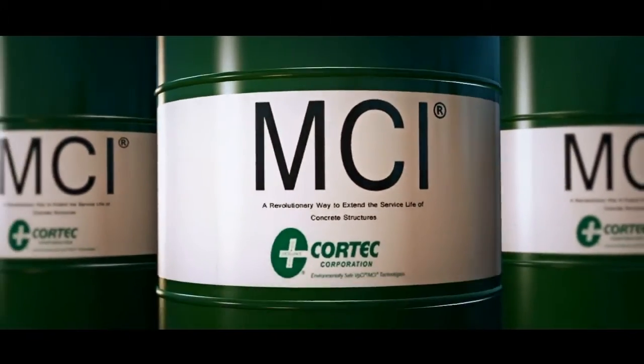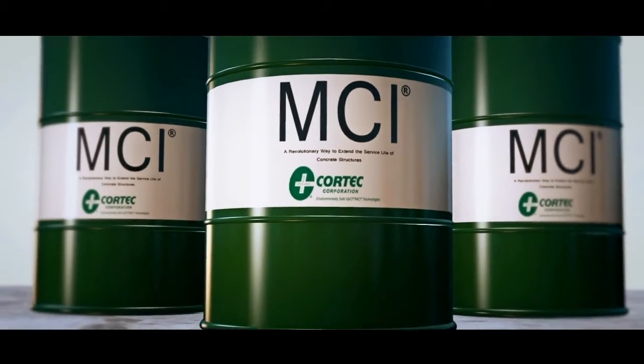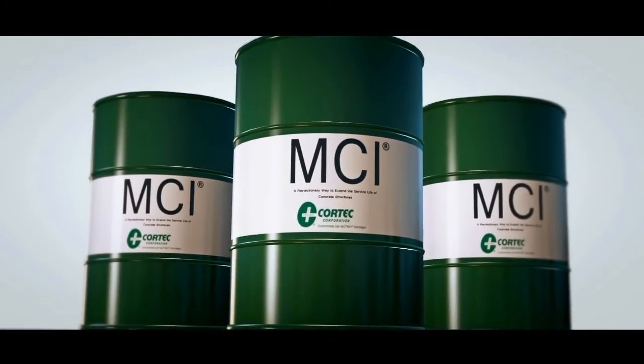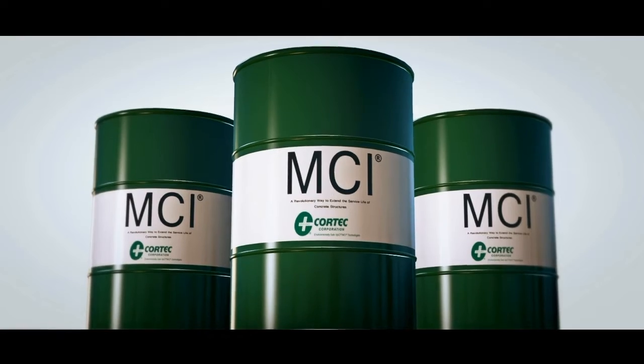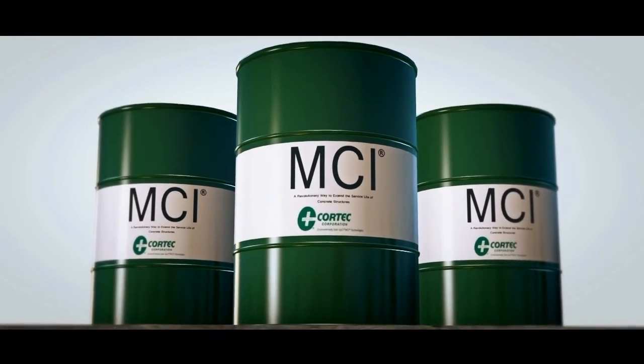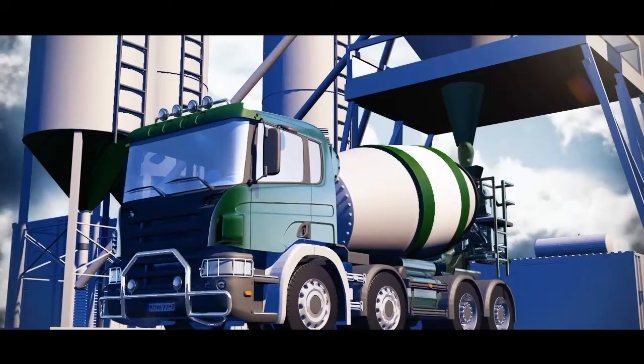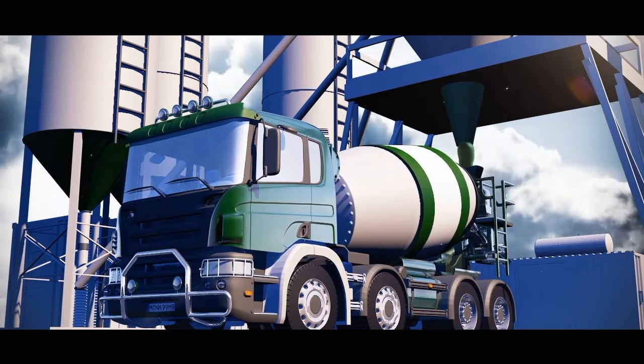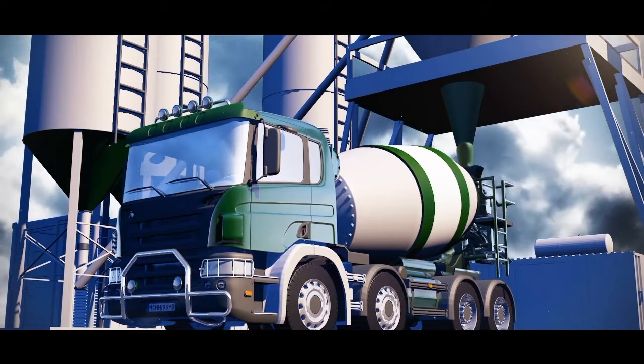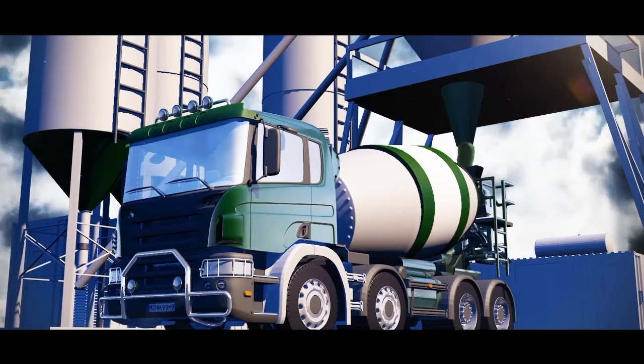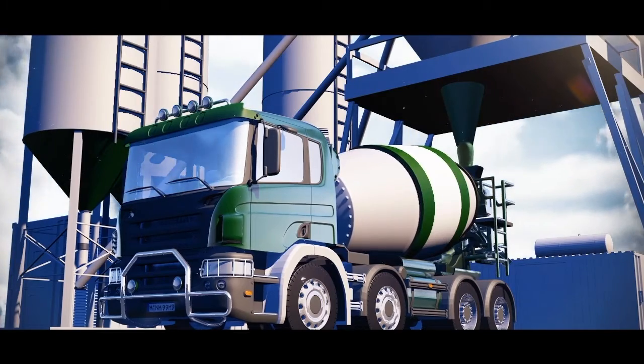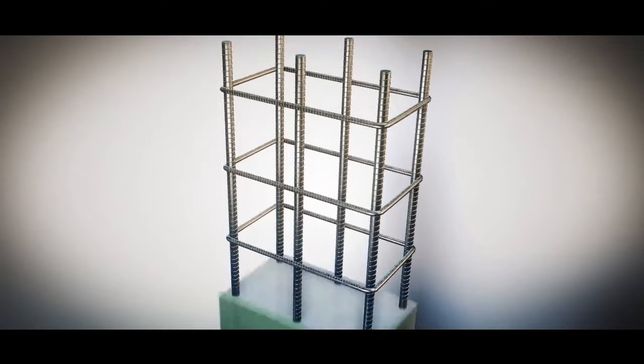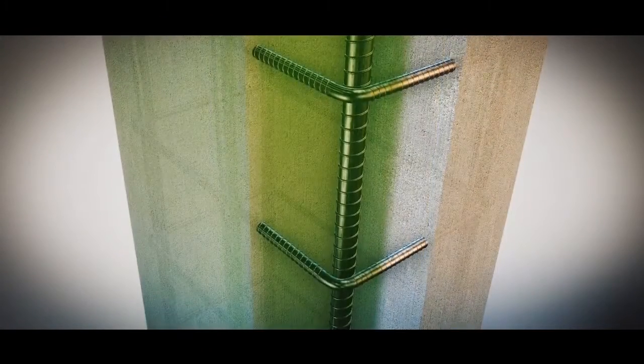Cortec Corporation has developed an effective solution with migrating corrosion inhibitors. MCI 2005 is a USDA-certified bio-based amine carboxylate admixture that meets ASTM C1582 requirements. MCI is added to concrete mixes at the batching plant, where it is dosed at very low rates. The concrete that is poured on site is saturated with MCI molecules ready for action.